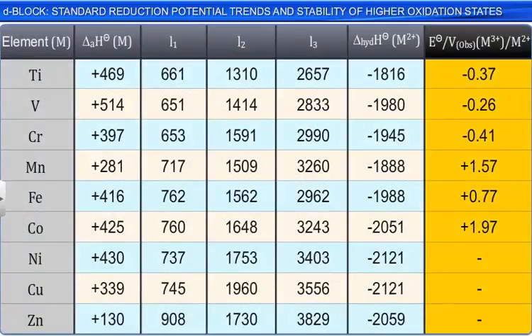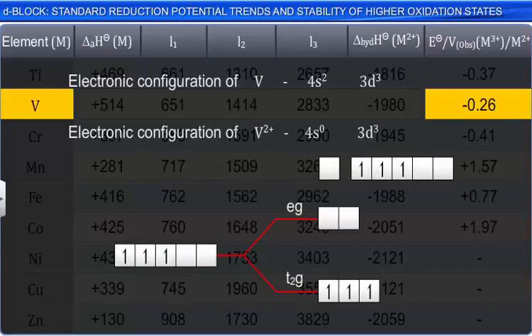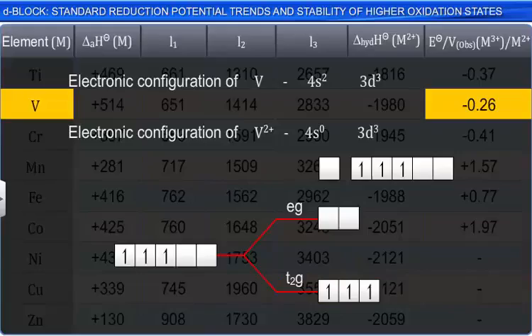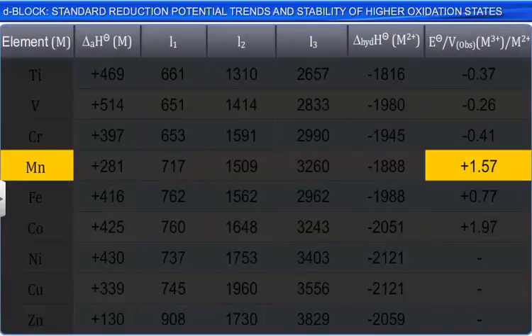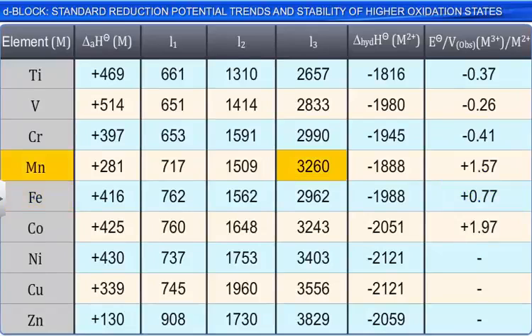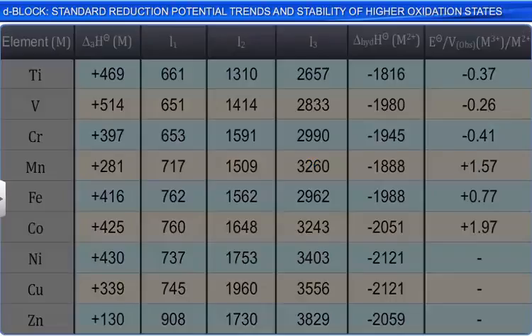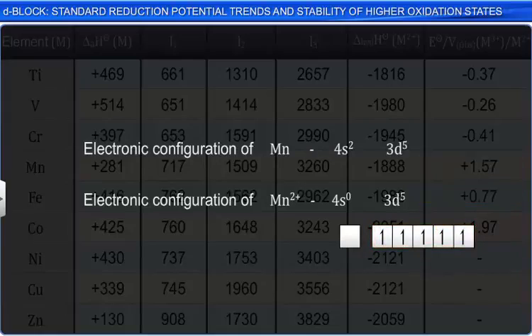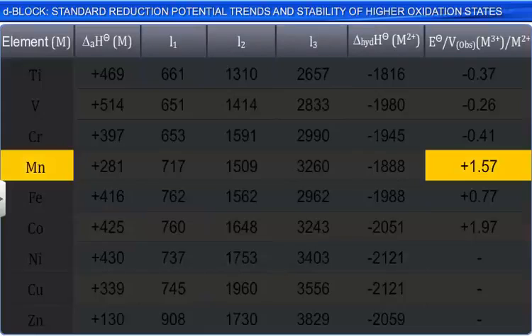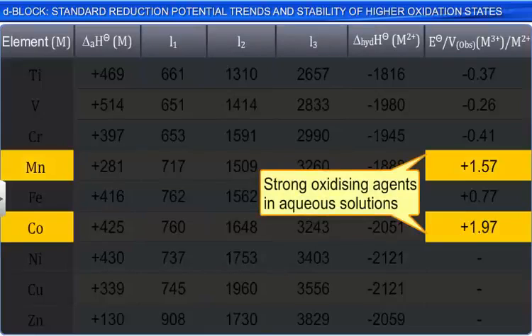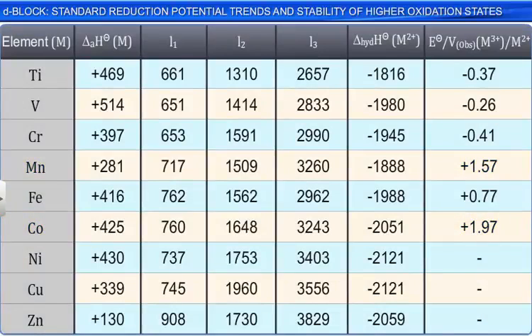The lower value for vanadium is due to the stability of V2+, as it has a half-filled t2g level. Manganese has a higher electrode potential value than chromium and iron because of its very high third ionization energy, which is again due to the stability of the half-filled d5 configuration. The higher values for manganese and cobalt show that they are the strongest oxidizing agents in aqueous solutions. The comparatively low value for iron shows that the reduction of ferric ion to ferrous ion is less favorable, since ferric ion is extra stable due to the half-filled d5 configuration.